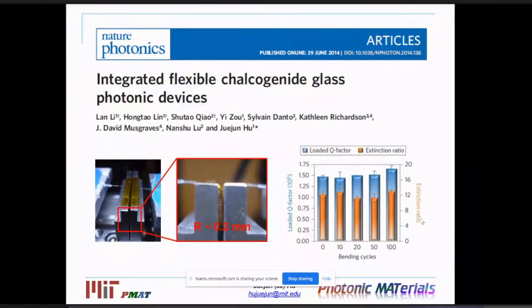Then we start by looking at integration into flexible substrates. A few years ago, we demonstrated monolithic integration of chalcogenide devices on a flexible substrate, and we were able to realize extreme mechanical flexibility. We can bend these devices down to a small bending radius of about 0.2 millimeters, essentially folding in half. We can also exert mechanical deformation over hundreds and thousands of cycles without seeing mechanical property degradation.